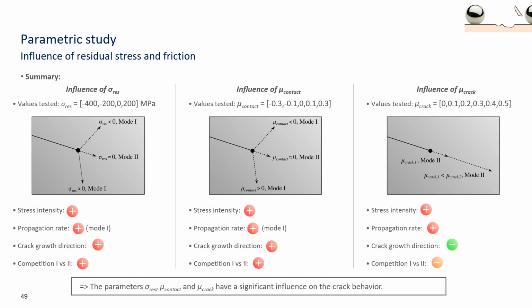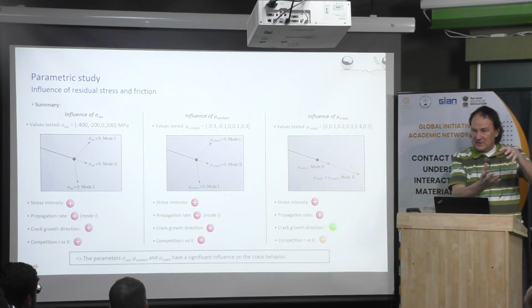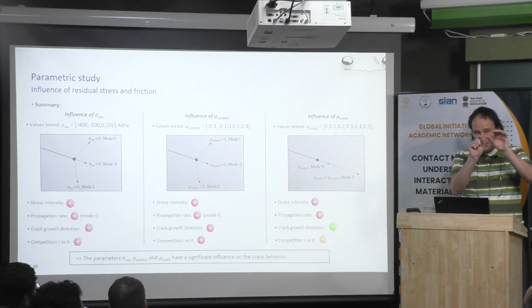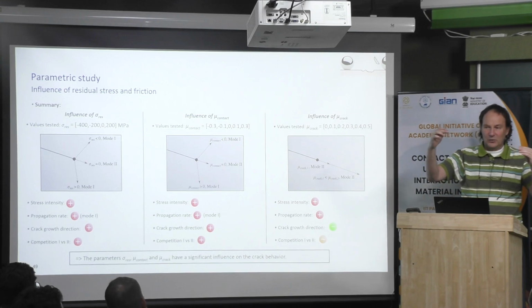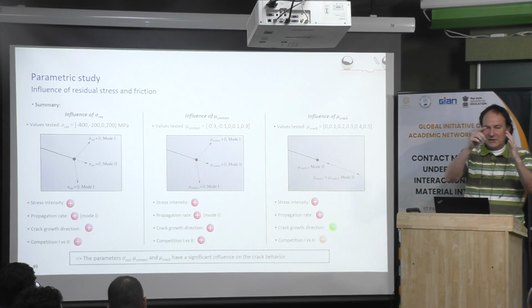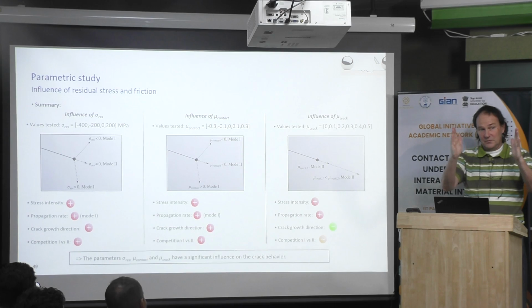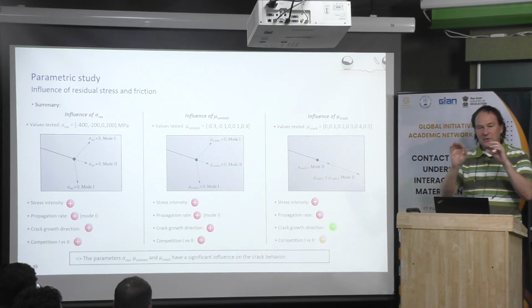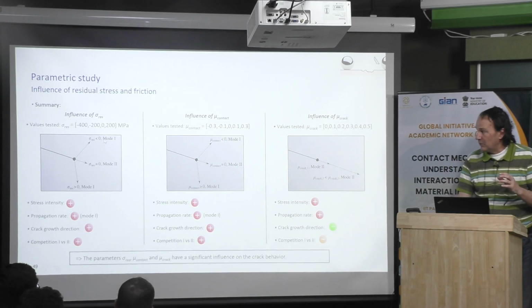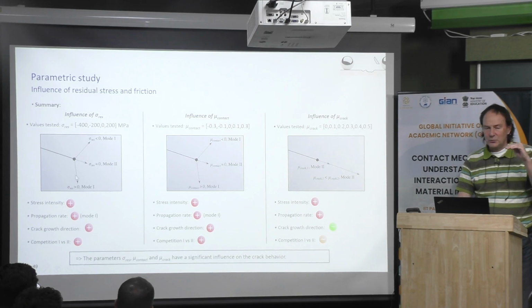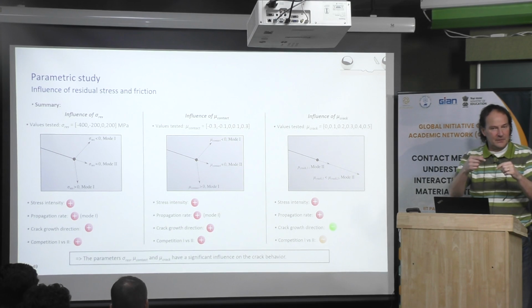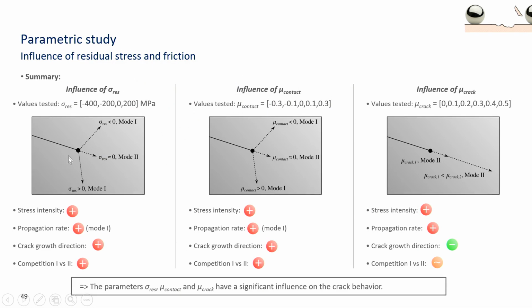Now, I don't know if you remember the machine. This is a gear, and there is a bearing integrated into the gear. But the gear is very thin, in fact. And because there are two contacts that are opposite, it is initially spherical, but it can become ellipsoidal, because there is some flexion, some bending, and the bending creates some tensile stress. Then even if at the surface you have some surface treatment, you may have some compressive residual stresses close to the surface, but when you pass the middle of the thickness of the gear, you always have some tensile stress, at least each cycle. And this is one of the causes why the crack branches like that and breaks the gear in two parts. And this is really a very important parameter.